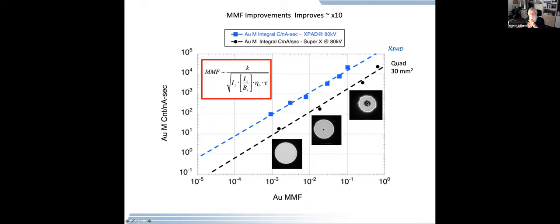So what I've done is I've taken that same nanoparticle and I measured it at different areal sizes. So I made the probe bigger, kept the same nanoparticle in view. And so the minimum mass fraction that it's occupying is getting lower and lower. We can see with a conventional detector, we're going down to the 10 to minus 3 range. As soon as we go to the X-PAD, with its higher efficiency, right? And remember, it goes as the square root of the intensity. So we're getting almost a factor of 10 improvement in terms of the minimum mass fraction, 10 times better than we could before.